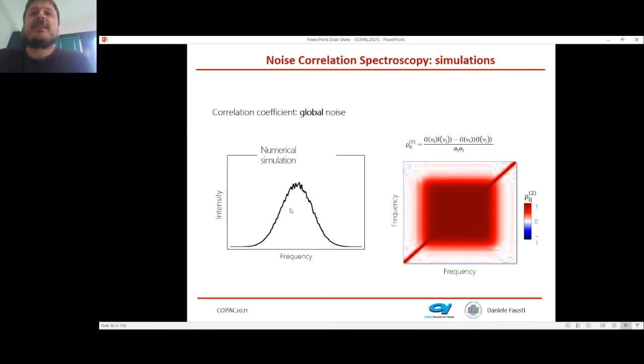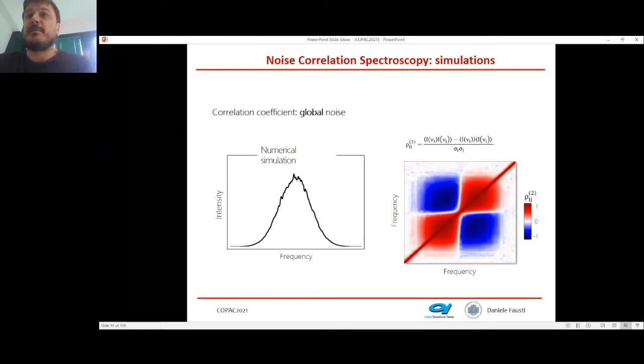What can I expect? For instance, this is a typical noise which you have on the laser, where your intensity fluctuates. If you measure the correlation pulse by pulse, you get something like a red blob on this frequency axis. This is the correlator as a function of frequency and frequency, showing how much the intensity fluctuations correlate. It's relatively easy to understand why, because if you look at one single measurement, the gray line here is the average and the black line is the single measurement. If the single measurement is above the average at one frequency, it's above the average at all other frequencies. So the correlation is positive between all the frequency components of my sample.